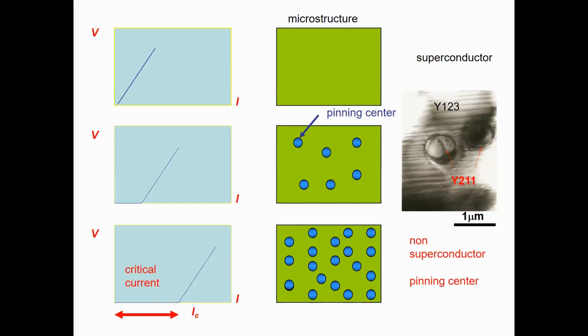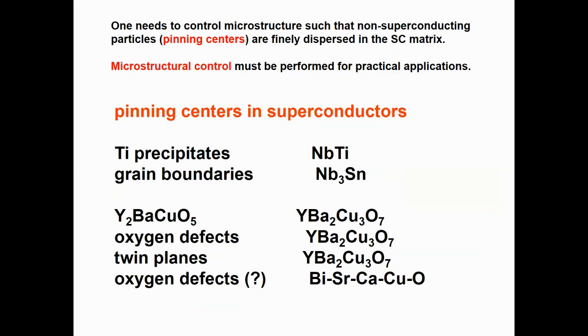That is key. In the case of yttrium-123, there is the yttrium-211 non-superconducting particle. Here is a TEM microstructure showing that very small 211 particles are embedded in the yttrium-123 matrix. So we need to control the microstructure such that non-superconducting particles, or pinning centers, are finely dispersed in the superconducting matrix. And lots of pinning centers are known in conventional superconductors, like titanium precipitates in niobium-titanium, or grain boundaries in niobium-tin, or 211 in yttrium-123.